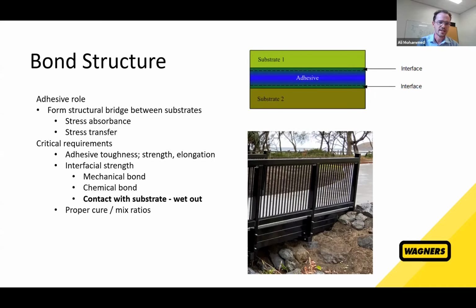The main critical requirements for an adhesive bond are obviously the adhesive properties themselves have to be strong and tough, and the right elongation to suit the expected stresses and loads. And then the details of the actual interfacial bond between the adhesive and the substrate. You want either a chemical bond, a mechanical bond, or ideally both. And then the actual wet out of those substrates via the adhesive is another function, and also governs the interfacial strength. So today we're looking very in depth at the wet out, or how the adhesive coats each substrate to give a very high surface area for the bond, so to speak. And obviously, there are other aspects to the bond as well, such as mixing your adhesive properly, curing it properly, etc., etc.